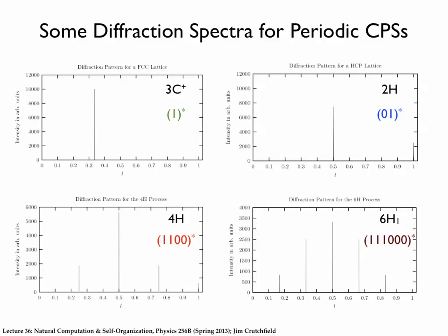Let's start talking about epsilon machine reconstruction and what it is going to look like. We talked about how to get the correlation functions from diffraction spectra, and just as we did on Tuesday, we're going to have to solve a set of equations to find sequence probabilities. Now that we have the correlation functions, these correlation functions are between the absolute layers in the ABC sequence. We want to actually use the Hägg notation and think of the sequences and find probabilities of sequences in terms of the Hägg notation,